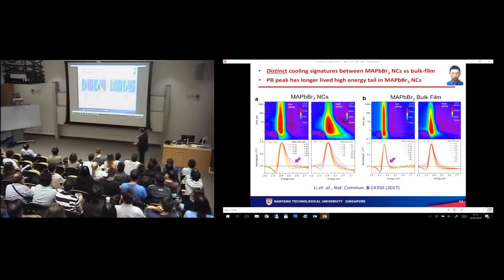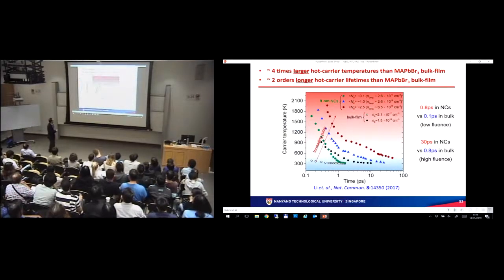So if you look at the high energy tail in your nanocrystals at low pump, this tail is much, much more pronounced compared to perovskite bulk films. So we have a fairly interesting phenomenon there. Now, this high energy tail, you can fit a Maxwell-Boltzmann distribution and try to determine the carrier temperature. So this is what we did, and we plotted this carrier temperature as a function of your lifetimes.